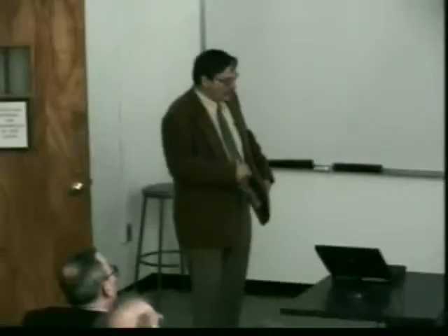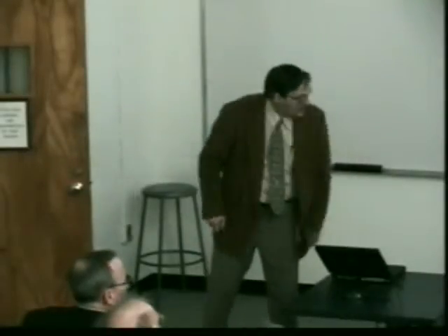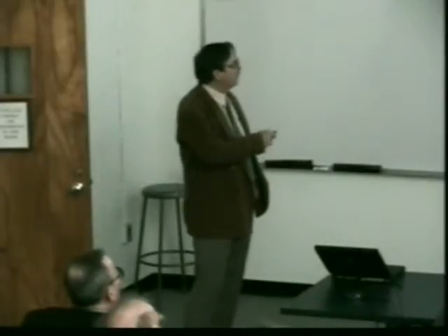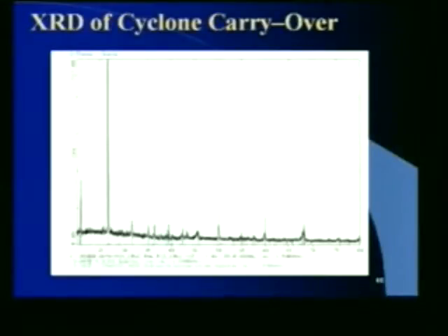We ran at about 30 kilowatts, feeding about 30 grams per minute of simulant and about 30 to 60 grams per minute of the borosilicate glass. These are the amounts of the simulant that we converted into the glass phase, ranging from 89 to 92%. There is some carryover; in these preliminary experiments conversions were typically 80 to 90%. The carryover, at least in these experiments, is primarily silica, as shown by this X-ray diffraction. This big peak here is silica, and there are some minor peaks of sodium aluminate in these particular experiments.